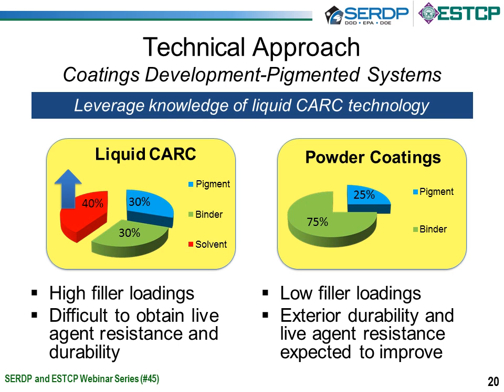So the technical approach we did, our background was liquid CARC. We have a lot of liquid CARC experience. So where does this differ? I'll point out that liquid CARC has 30% solvent in it. So you have a combination of solvent, or 40%, and pigment and binder there. So you see equal parts, and we call it a pigment to binder ratio of 1 to 1 with 40%